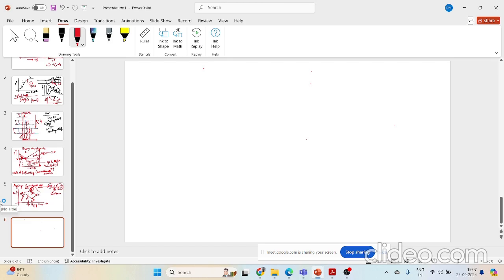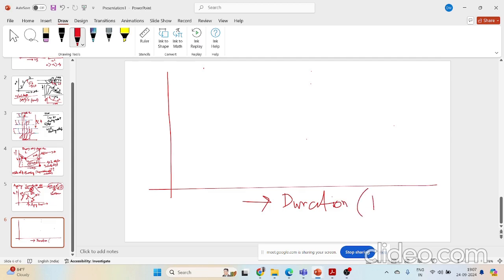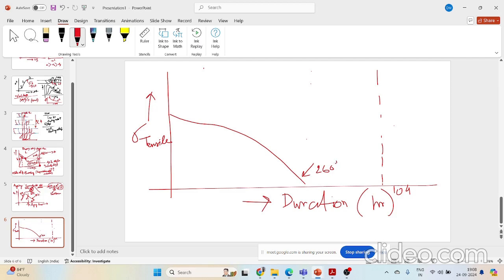So let's say this was the duration in hours. The maximum was somewhere around the order of 10 to the power 4. Okay. And this is my tensile strength, sigma tensile. Fine. So with increase in duration, the lowest one will be at the highest temperature. So this was aged at 260 degrees C.